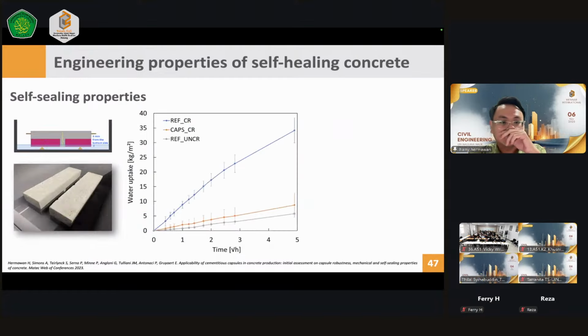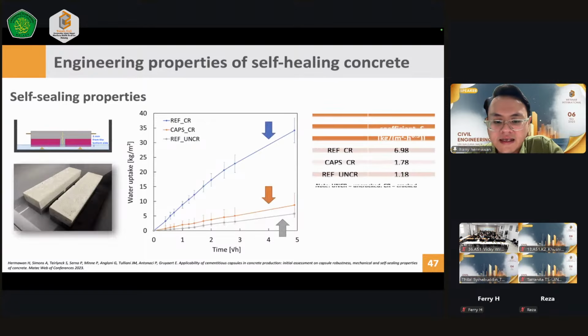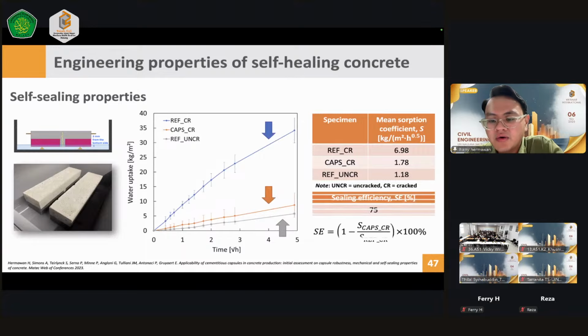And with the same test, with the capillary water absorption, we can also check what will be the performance. And in my research, we also found that the sealing efficiency with the macro capsule can reach 75%, which is quite high if we compare with the reference concrete.